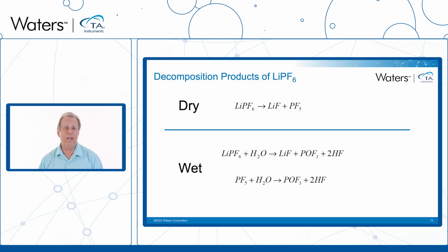Now I'm going to move on to looking at LiPF6 in these pans. So I want to first off review what the decomposition of this material is under dry and wet conditions. So if LiPF6 is dry, if it hasn't been exposed to water vapor, it will decompose into LiF and PF5. Under wet conditions, LiPF6 will decompose to LiF, but it will also decompose to POF3 and HF. And the PF5 that is produced during the main decomposition event can also react with water and produce those same 2 components, the POF3 and the HF, when it decomposes as well.